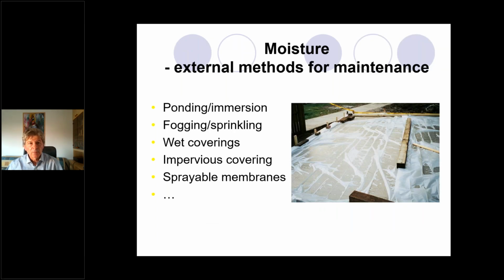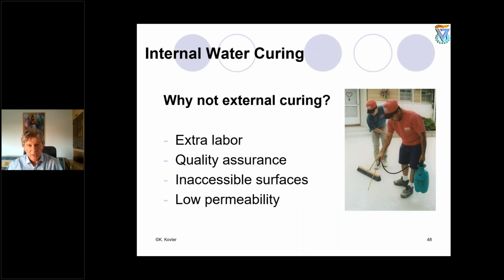So again, moisture, external methods for maintenance. But why not external curing for high strength concrete? First of all, external or conventional methods of curing require extra labor. We need to take care about quality assurance, quality control and insurance. Insurance, by the way, is more important than control. We have, in many cases, inaccessible surfaces. And especially when we discuss high strength or high performance concrete made of very low water cement ratio, this concrete is low permeable. It means the water applied from above, from outside, cannot penetrate too deep, more than 2-3 millimeters. You can neglect the penetration depth, so it doesn't help to cure.